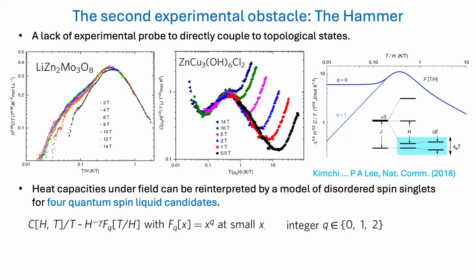You measure that heat, then you compare with the experimentally measured heat capacity in the field for 4 different spin liquid candidates. You realize they all scale in this kind of bumped shape, like his theory would predict. Right, so this is a very simple shape, and they can model a different type of physics, and then your experimental data actually can match with that.